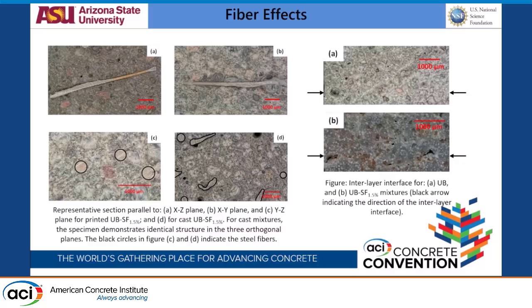So when we saw the cross-section image along the interlayer joint of the beams, what we observed, in the figure that you see on the right, is that the system is such that we only used 1.1% SP and we just kept on adding the steel fiber. So with a high volume percentage of steel fiber being added, the mix gets stiffer and stiffer. At 1.5%, we saw that along the interlayer joints, though there was no void initially, for these samples there are voids. So somehow this void formation and the fiber alignment are cancelling each other out, and that's why we see the cast sample perform comparably to the printed sample. So that was our observation from flexure.